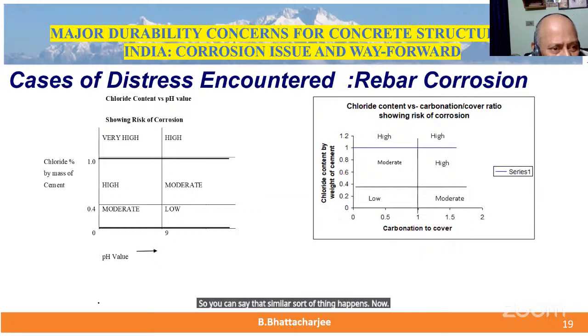Now this 0.4, chloride by mass of cement, Bungey suggests that you can take it to equivalent water-soluble chloride in this manner. Bungey, or there is another book, I'm not sure, 0.4% acid-soluble chloride, because that includes chloride that is bound chemically, and physically also part of it. So 0.4 divided by 7.5, because cement content was around 1:7.5, cement to total concrete. They took it as 7.5. And total chloride to free chloride, total chloride divided by water-soluble chloride, is around 1.55 times. So 0.034 water-soluble chloride, and equivalent could be thought of, but by mass of concrete is what we will measure. In an existing structure, you can measure only by mass of concrete.